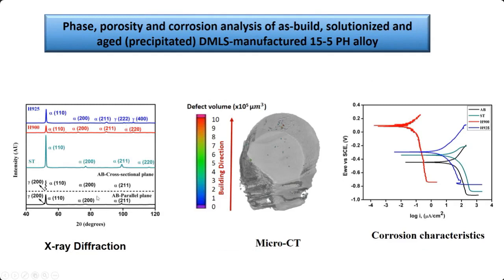The as-built structure has also been studied at the cross-sectional and parallel plane to find out the differences. We have also done detailed porosity analysis, and most importantly, the corrosion behavior. A detailed systematic investigation has shown that if we are aging it to H900, the condition is here.